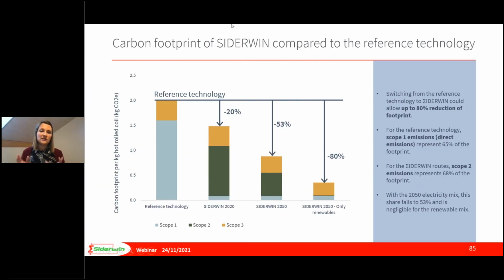And we can finally see here the carbon footprint of Siderwin compared to the reference technology of blast furnace, basic oxygen furnace. So we can first observe that switching from the reference technology, which has a carbon intensity of 2 kilograms CO2 equivalent per kilogram, to Siderwin could allow a reduction of up to 80% for the carbon footprint.